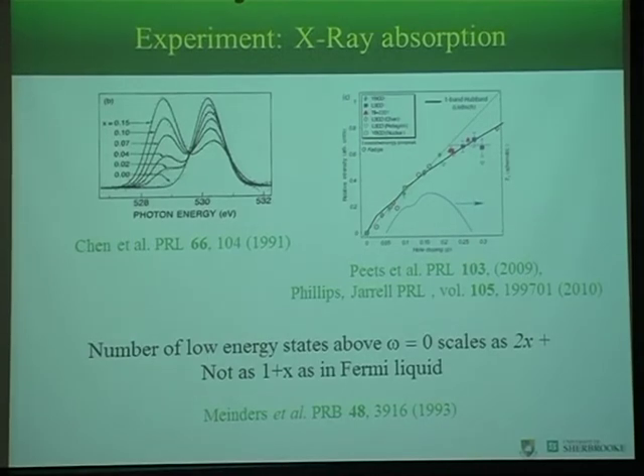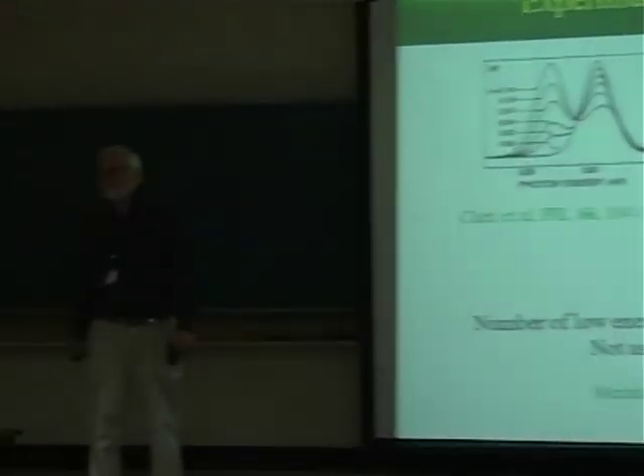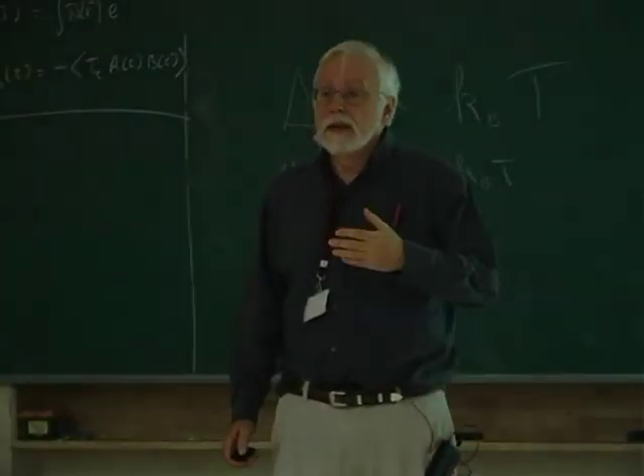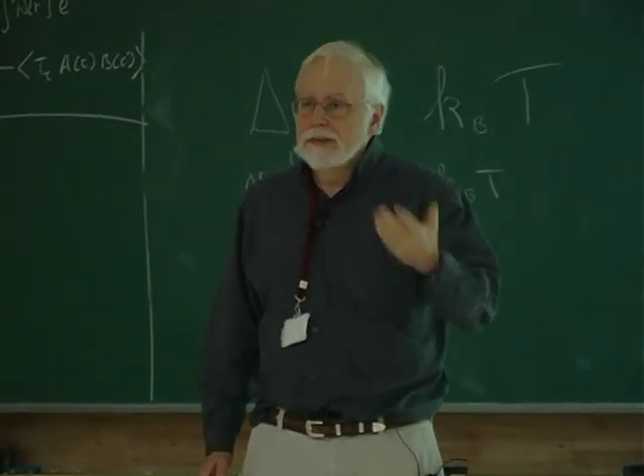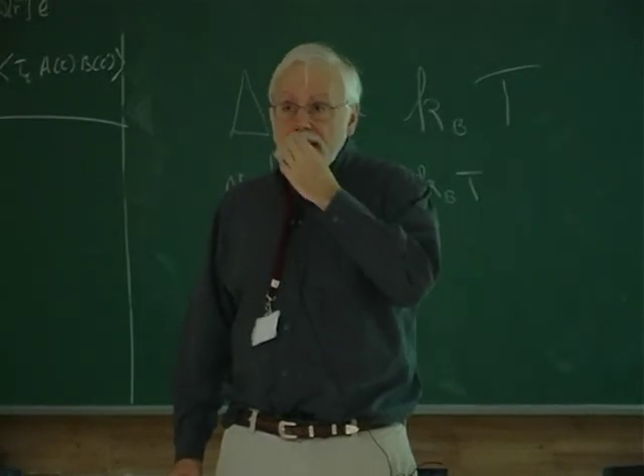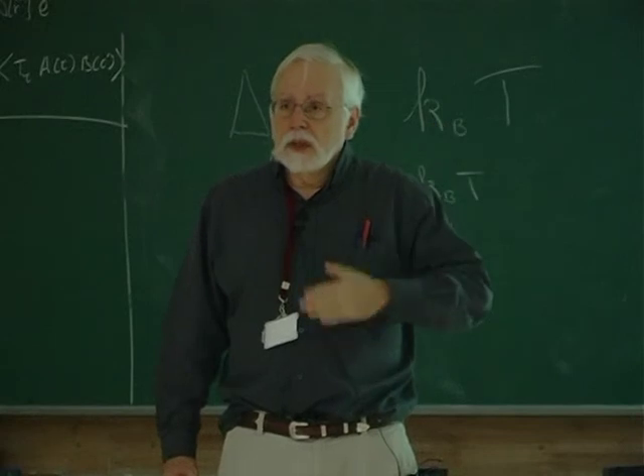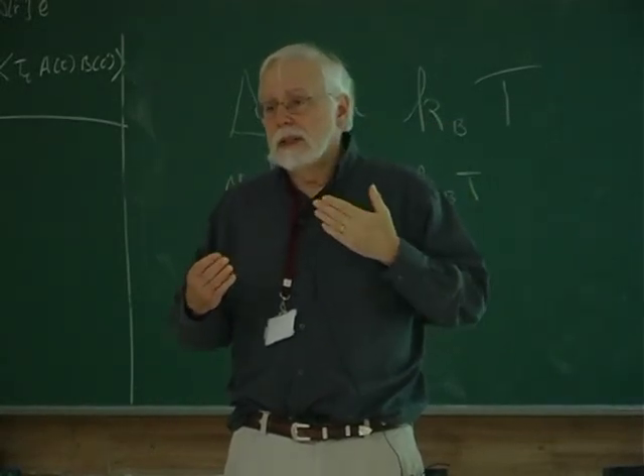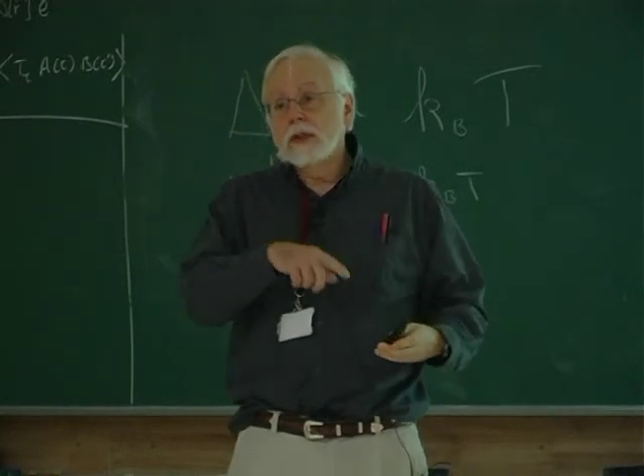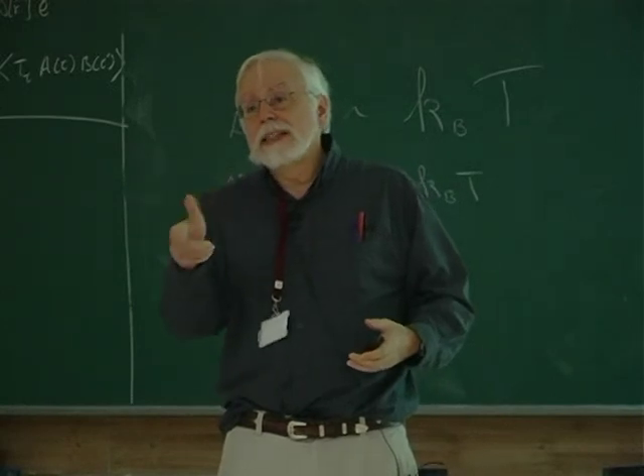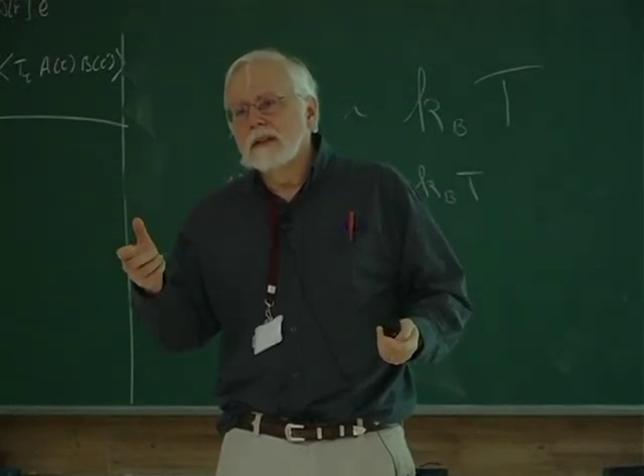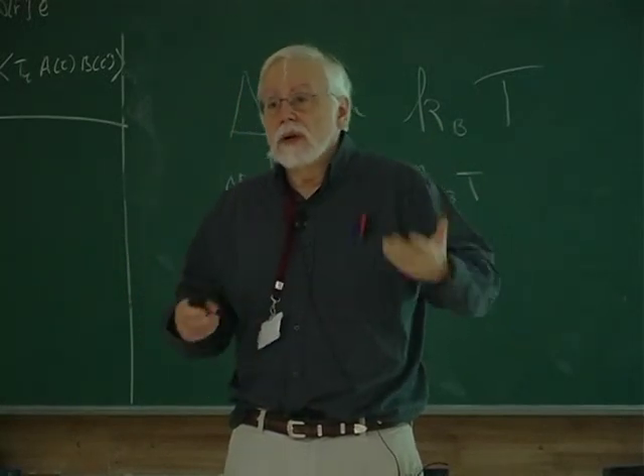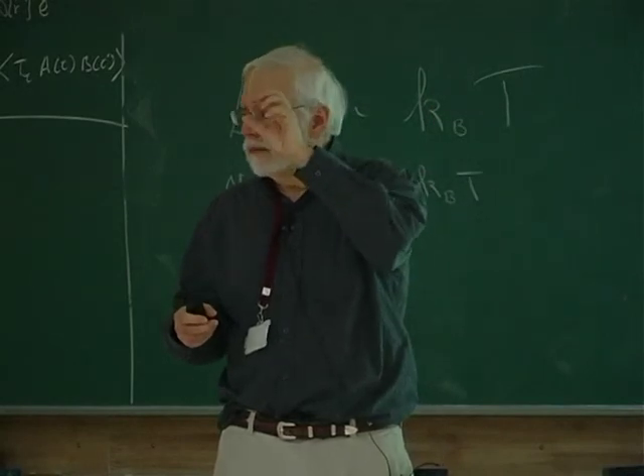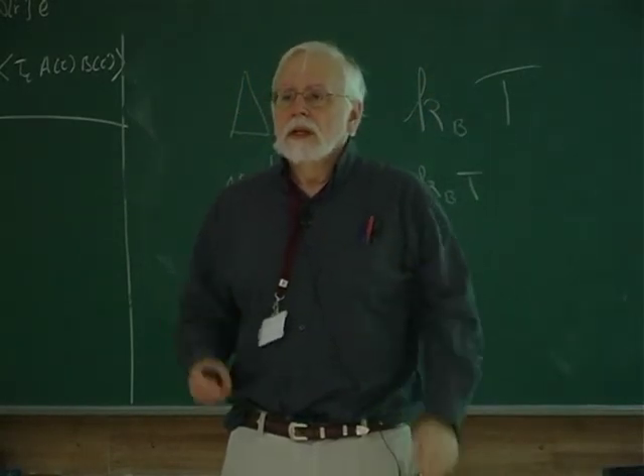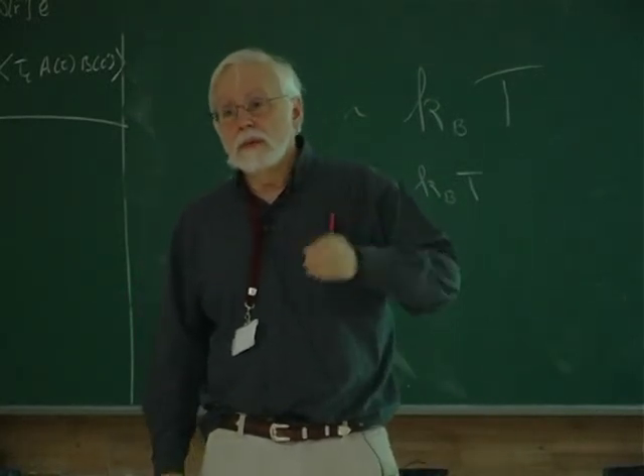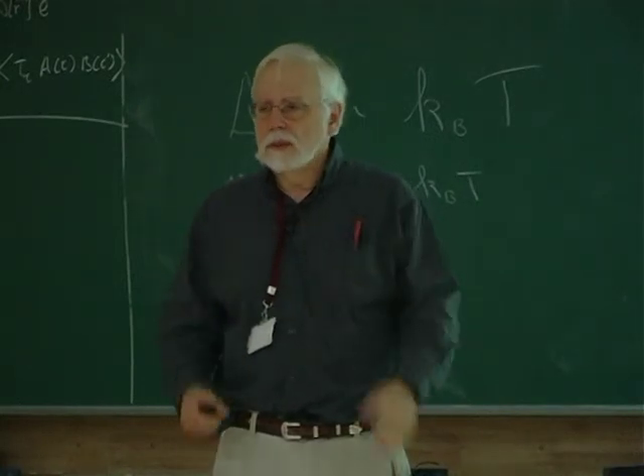Yeah. And one more thing, how is the correlation or coherence length calculated through experiments? Okay, the correlation lengths that are shown were antiferromagnetic correlation lengths. The way you do that experimentally is that you measure the neutron scattering cross-section, and from this you extract the spin-spin correlation function. You look at it as a function of wave vector, and then the half width at half maximum is a measure of the inverse correlation length. So it's a rather direct measurement. All the form factors are known because this is just dipole scattering, neutron scattering off the dipoles of the spin, so it's quite accurate. You don't know the absolute value, but you certainly know the widths and so on.